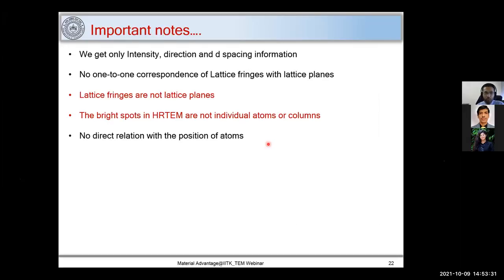Now, a very important point which I have touched upon in HRTEM is that we only get intensity, direction, and D spacing information. Most of the time, people get confused between lattice fringes and lattice planes. What we see in HRTEM images, like the images which I have shown earlier, are lattice fringes. Those are not lattice planes. Thus, the bright spots in those HRTEM images are not individual atoms. This is a very important point.